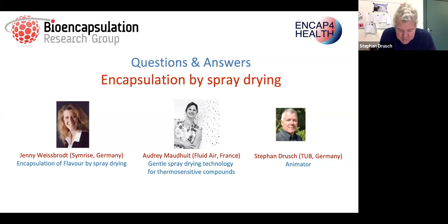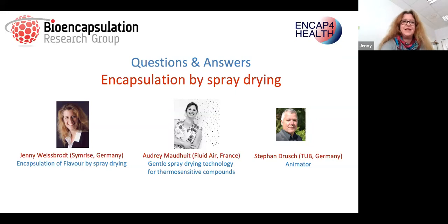The first one was: Jenny, if you have any idea on how to compare the behavior of modified starch and gum arabic or maltodextrins with different DE. This would take a day to make really concrete. Modified starches are standardized substances which always have the same nice emulsifying properties and even drying properties. Gum arabic is a natural product which will change a lot during the seasons and maybe even from one supplier to the other. Maltodextrins can be divided by their DE value. If you have a high DE value, you have smaller molecules, less viscosity, but a higher hygroscopicity. A low DE value means you have a bigger molecule, less hygroscopicity, but a higher viscosity. This is a very short version.